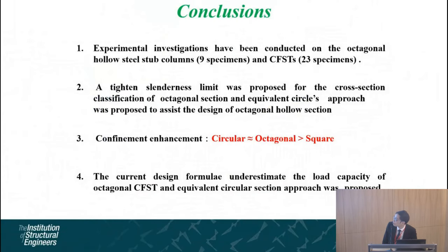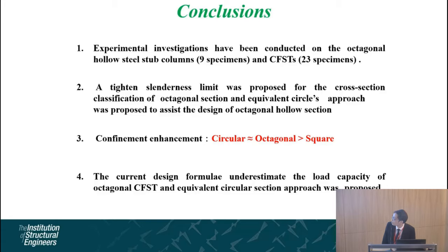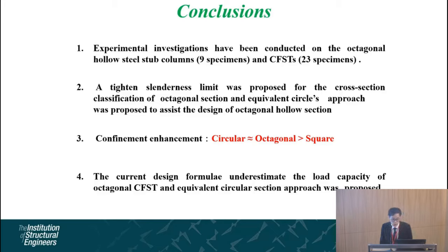In conclusion, we conducted experimental investigations on hollow steel tubes and concrete-filled steel tubes with octagonal sections. We propose a slenderness limit for the octagonal section using an equivalent circle approach. The study of confinement shows that the confinement effect of the circular and octagonal sections is almost the same, both better than the square section. We also propose a design formula to predict the load capacity of the octagonal concrete-filled steel tube. Thank you.